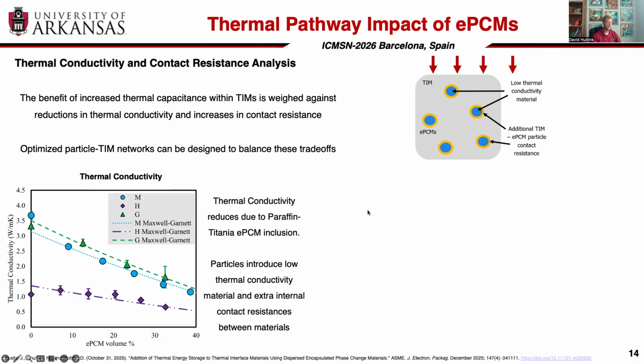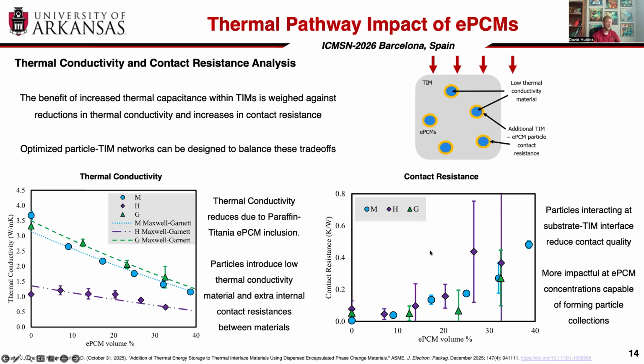We do see a reduction in thermal conductivity with addition of particles, and this largely has to do with the percolation network of thermal pathways through the TIM. The TIMs themselves include particle loadings that are high conductivity to try to improve this. So by integrating into that network, we're actually reducing some of that network, and it does follow classical models quite well. But we also can see that as we add more particles into the system, we do see more contact resistance arising too, because essentially we're creating a new material interface that is not well tuned for the system.